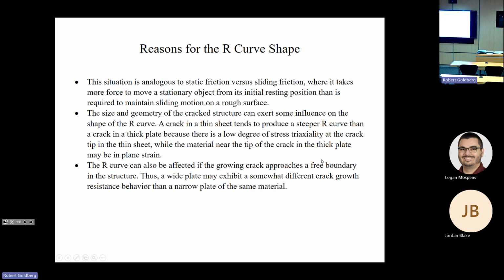So a crack in a thin sheet produces a steeper R curve than a crack in a thick plate, because the thin plate is closer to a plane stress problem. So we have a low degree of stress triaxiality at the crack tip, whereas in a thick plate, not only is it not plane stress, but it may actually be in plane strain. So you'll have stresses in all your directions, and that increases your local stress concentrations, which can facilitate crack growth.